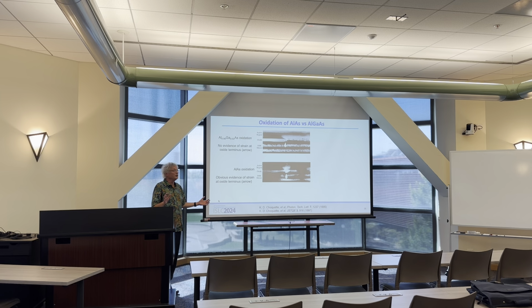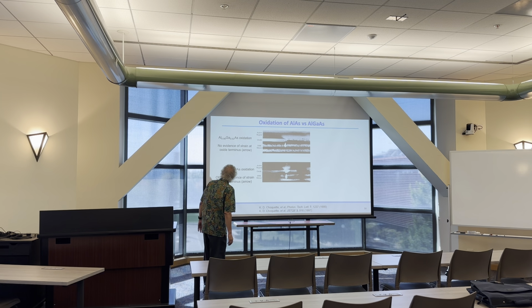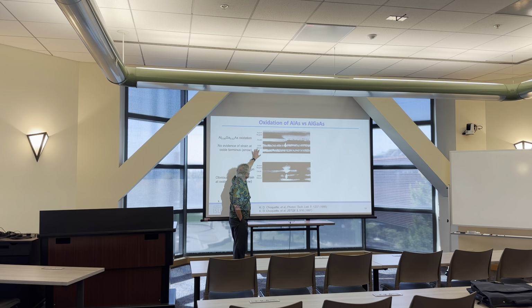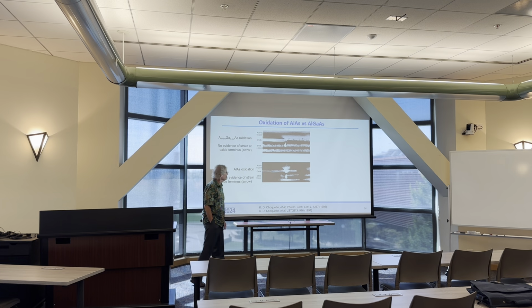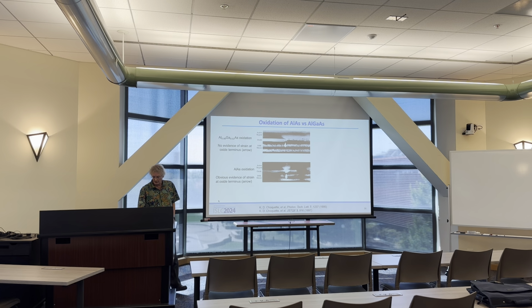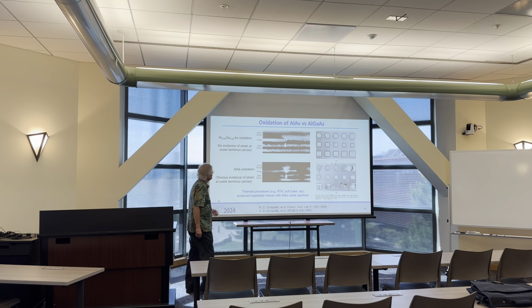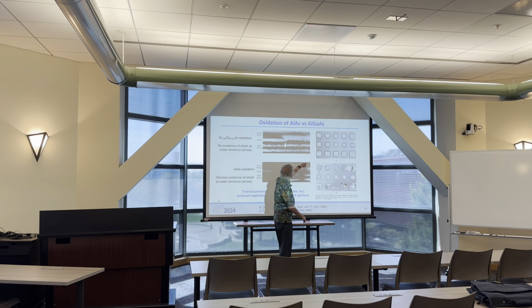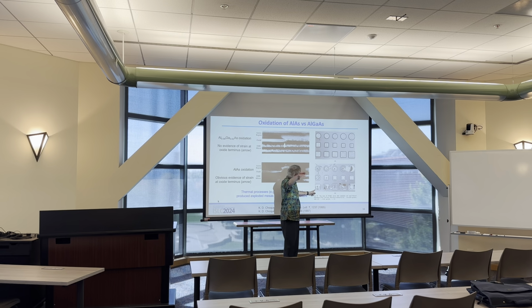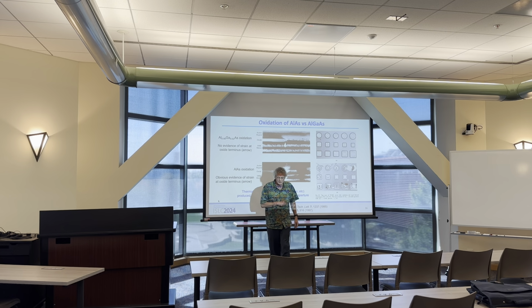We learned why you want to use AlGaAs. Basically this is a structure using AlGaAs, this is a structure using aluminum arsenide, and the key difference here is that the pure oxide gives you a lot of strain. It's not obvious in this image, but this is a structure looking down at the oxidized mesas using AlGaAs. If they're using aluminum arsenide, they explode. And the joke I made that just went right over everybody's head was that, well, these explosions were too small to be noticed at Sandia.